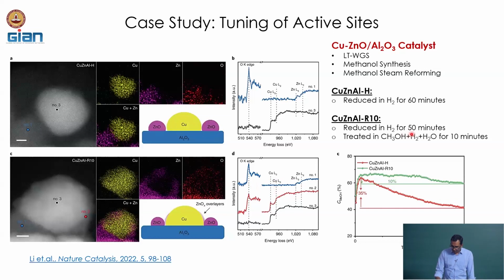Whereas, if we treat it in hydrogen for 50 minutes followed by treatment in methanol, hydrogen and water, what we see is that part of this zinc oxide now migrates to stay on top of these copper nanoparticles, as seen from the image. So, in one case we have the zinc oxide and the copper present next to each other on the alumina support. In the other case, the zinc oxide and the copper are present, but now a part of the copper is covered with some form of zinc oxide, ZnOx.